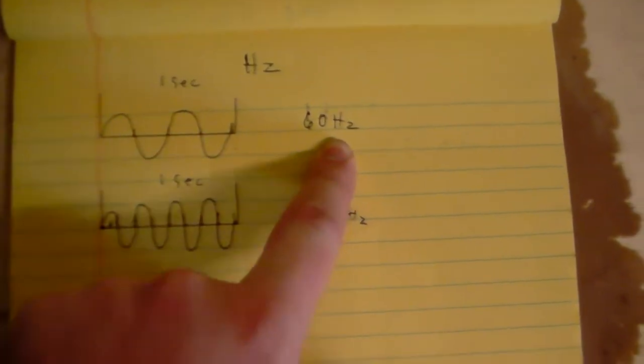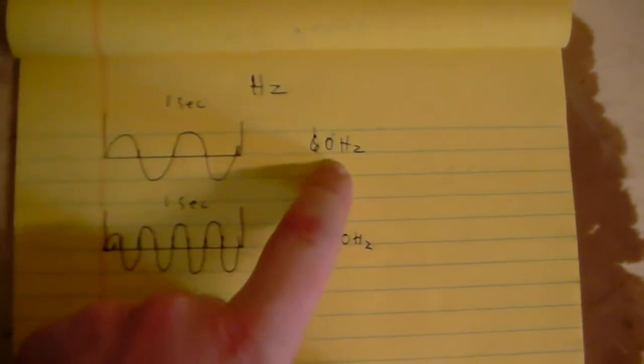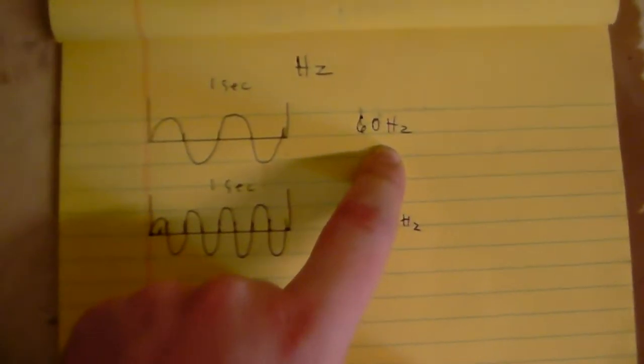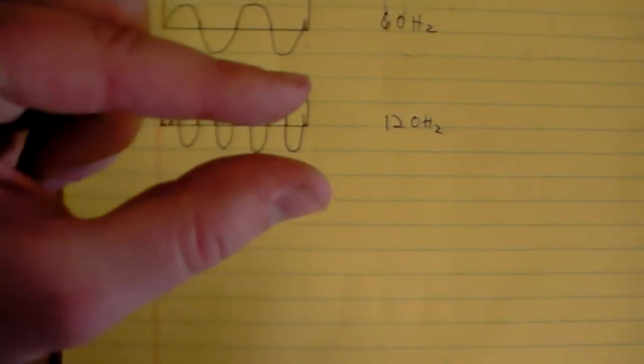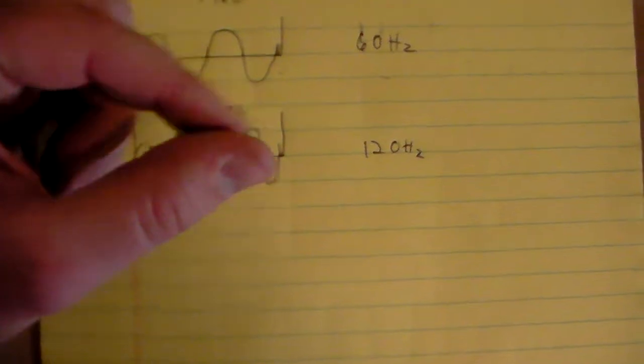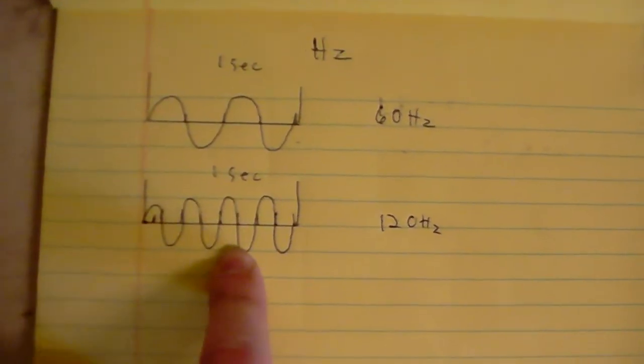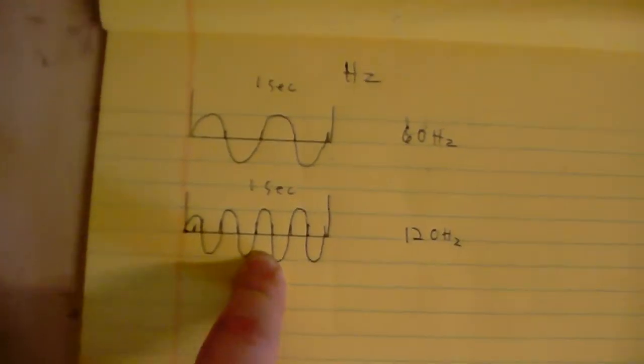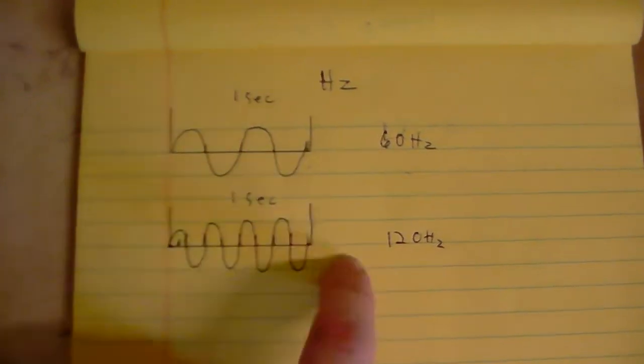So lower hertz generally used for welding thicker aluminum, stuff that you got to put some heat into in order to get it to weld correctly. Whereas as you increase your hertz, you spend less time at your peaks and you have more 0 points. So it concentrates your heat down, giving you a more narrow and concentrated bead. Much better as you start getting thinner and thinner on your aluminum. A bit more wide and a bit more heat into the puddle as you get into thicker aluminum. So that's kind of the general concept with hertz controls and why you want to use them.